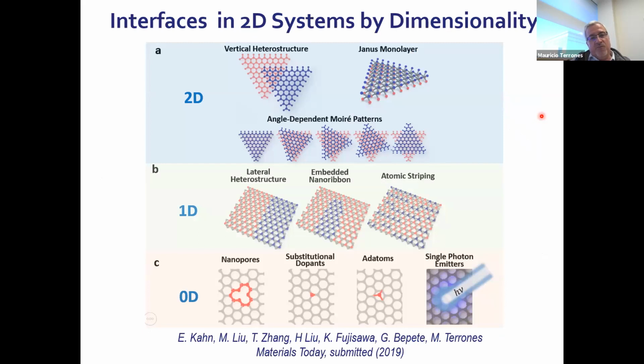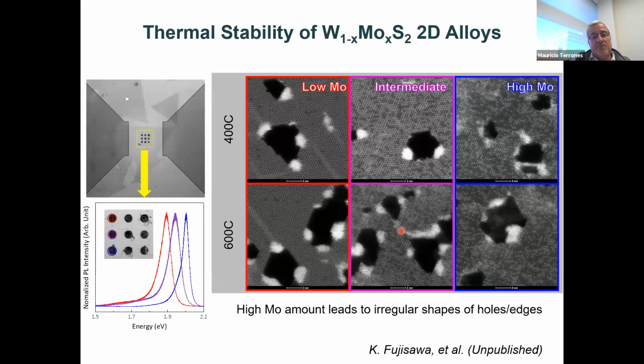So, I mean, there are different ways, different dimensionalities of defects. But what I wanted to show here is that sometimes you have these lateral heterostructures with tungsten and moly sulfide that I showed. And you have these interfaces, or you have this sort of system with atomic stripes, so you have stripes of moly or tungsten in the system. But when you try to heat these monolayers, and you have an alloy of tungsten and moly, are these more stable, right? Or what happens to them?